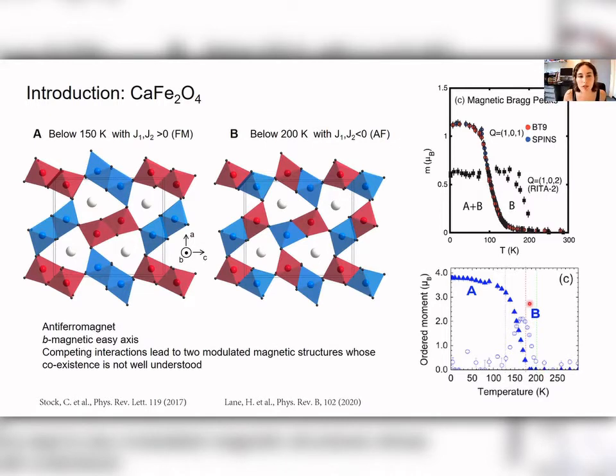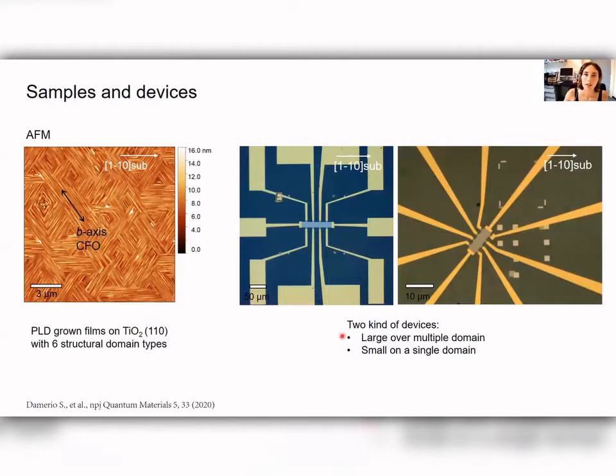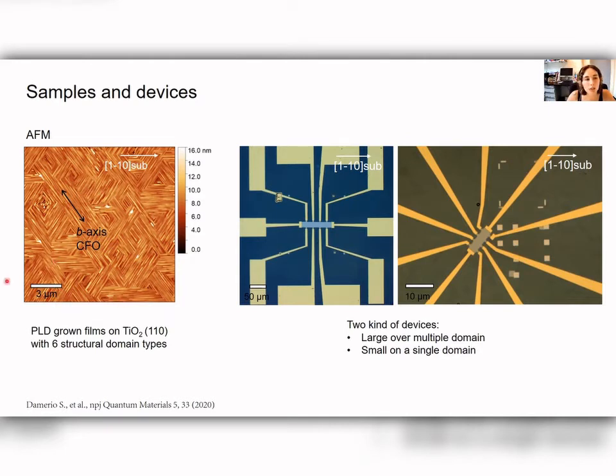We wanted to utilize the spin Hall magnetoresistance experiment to gain more information about the order parameter and magnetic behavior of this material. The samples used are thin films of calcium ferrite grown by pulsed laser deposition on TiO₂ (110) substrates. As seen in AFM images, our films are not a continuous single-domain film but are composed of multiple structural domains, which are easily identifiable by the surface topography.